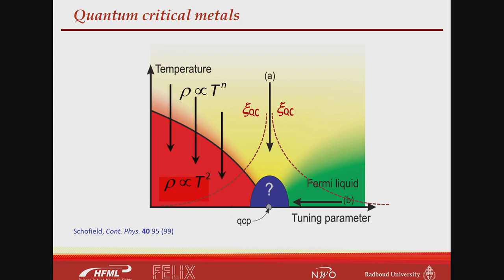And then of course you have an additional thermal length scale, which gives rise, the combination of these two, this diverging length scale and the thermal one, gives you rise to this quantum critical fan. And perhaps then if you're measuring transport in this metallic system, where you have fluctuations associated with this ordered state, you may end up with some anomalous power law in the low temperature resistivity, like four-thirds or five-thirds. And then as the system becomes ordered and those fluctuations gapped out, you then recover your Fermi liquid behavior. But above that, in this quantum critical fan, you may then get other anomalous non-Fermi liquid power laws. But right at the quantum critical point, you should see that anomalous exponent tracking all the way down to the lowest temperature.